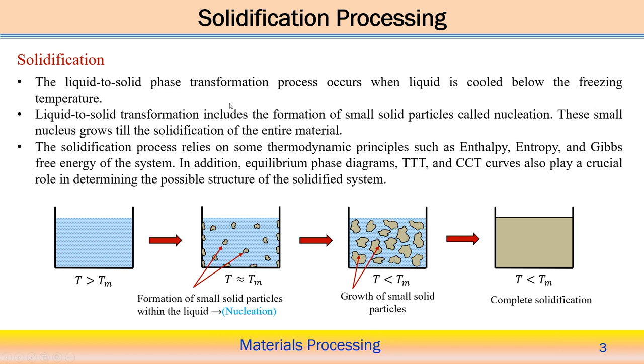When small particles form, that is called nucleation, the transition from the liquid to the solid phase. After a certain period of time, these particles will try to grow, and that is the growth of the small solid particles. This growth phenomenon usually occurs below the melting point temperature. Once the liquid has completely transformed to solid, we can say the solidification is complete. The bulk temperature of the material should be below the melting point temperature. So these four different steps of solidification are very clearly shown in these figures.